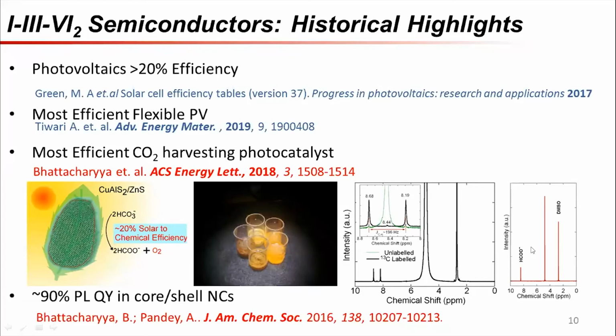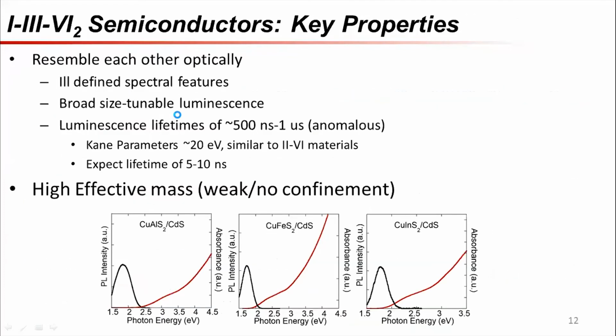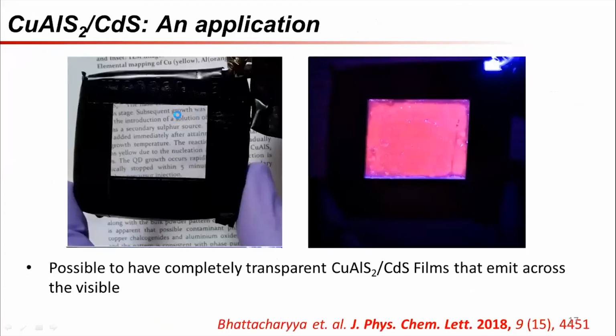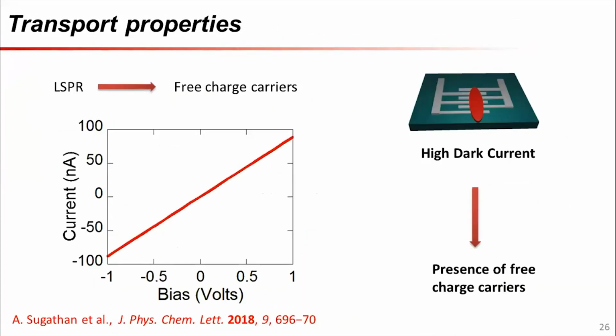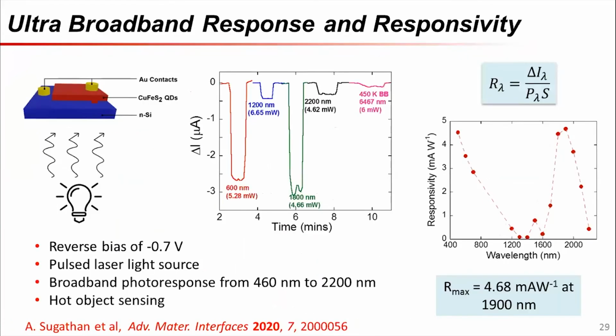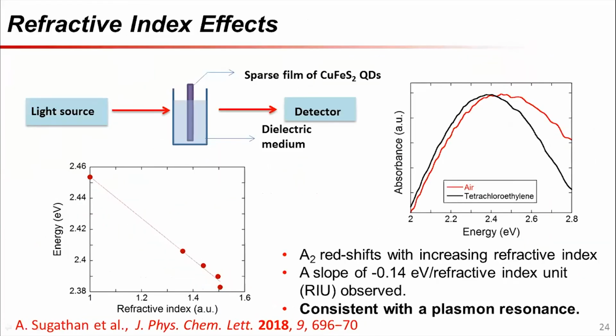So going back to the experiment which I had described, I think it's right here. Going back to this particular experiment, I said that we have used sparse films of copper iron sulfide nanocrystals. There's a good reason to use a sparse film. Sparse means that the nanocrystals are far apart from each other, and if they move very close to each other, we see that they couple, and there is a strong redshift of this plasmonic feature. So it is very sensitive to its environment, and even other nanocrystals count. Their coupling itself shifts this. So that's definitely happening here, and that's why we investigated sparser films.